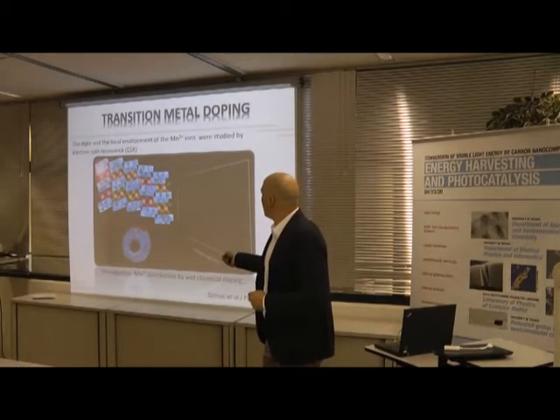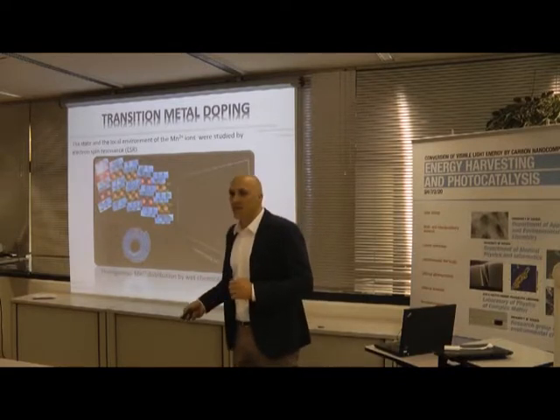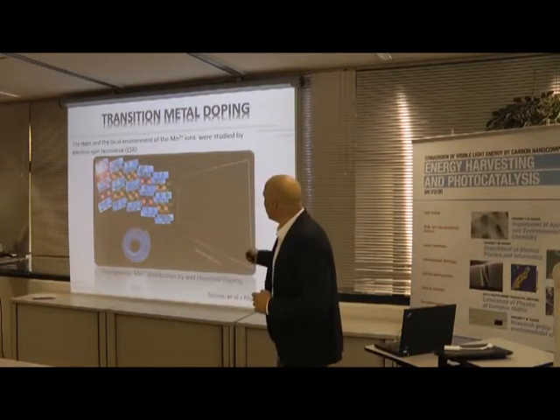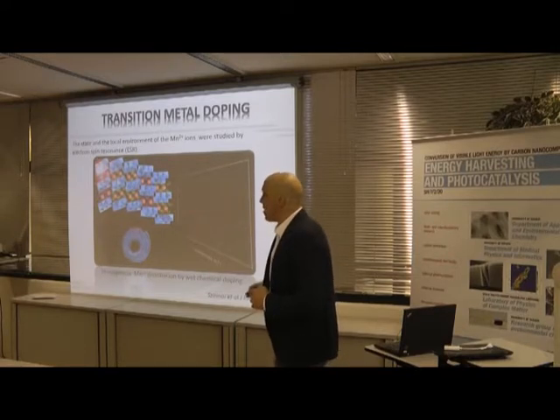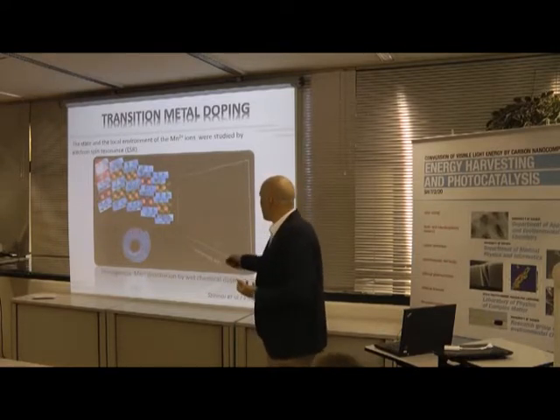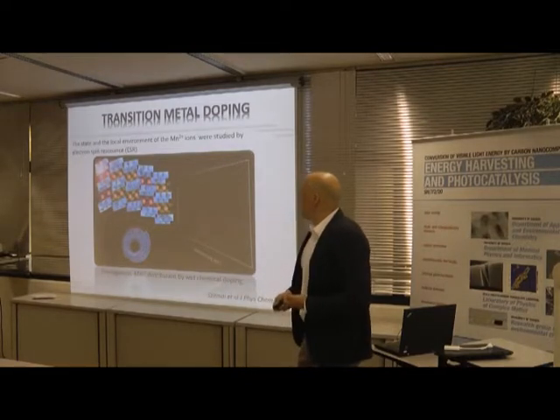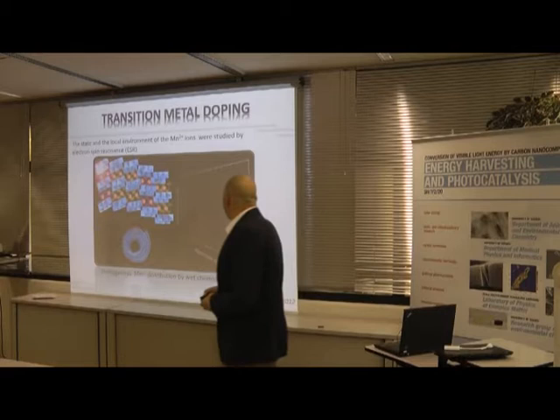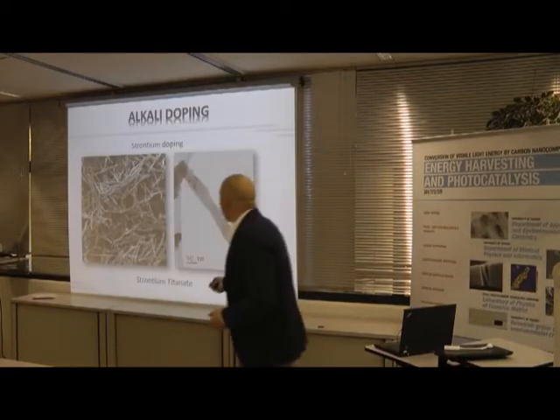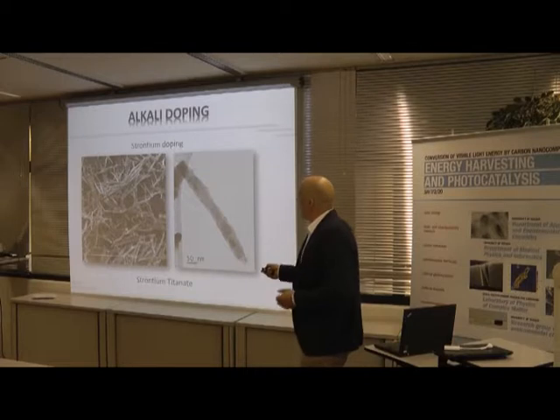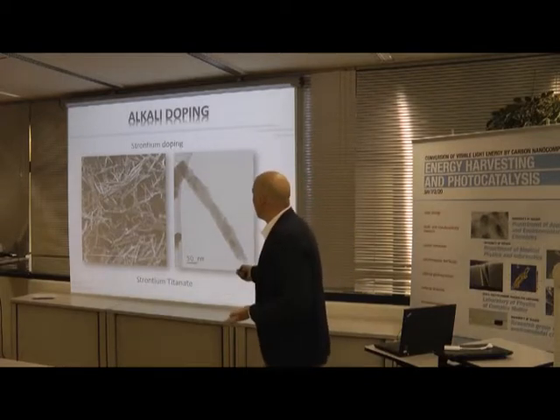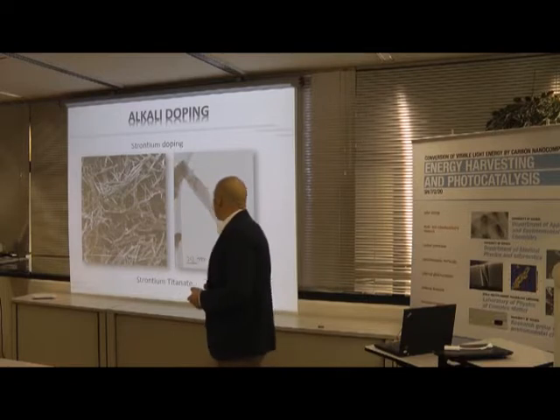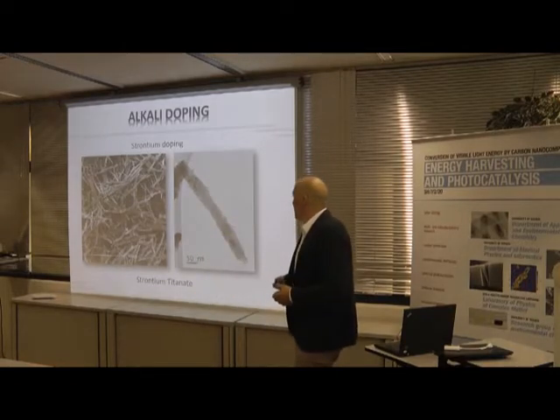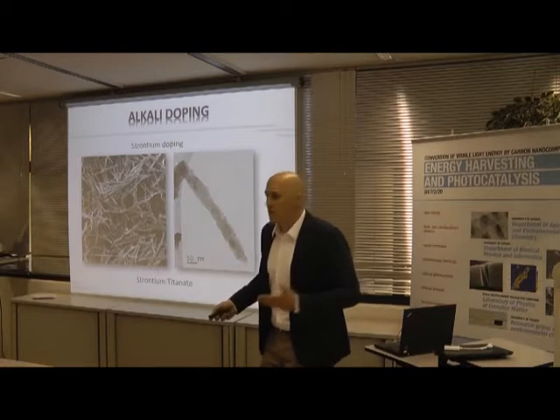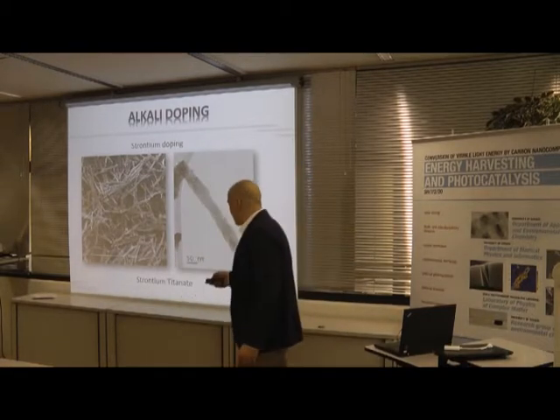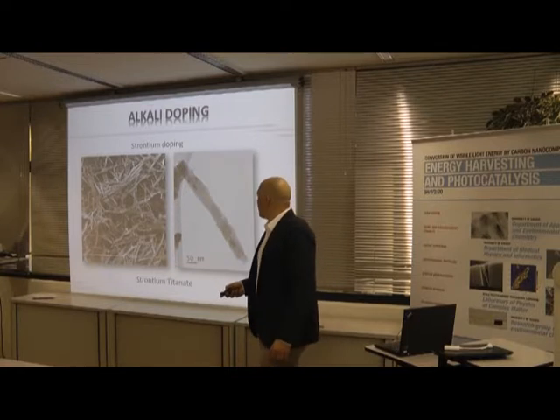Here is a case when we use the ion exchange properties of titanium nanotubes to put manganese into the structure, and that the manganese was homogeneously doped within the framework was proven by EPR, electron spin resonance, by Peter Szirmai and Bálint Nafradi. Another, we can use alkali doping. Here we increase the doping alkali ion concentration so much that we completely render the titanium oxide into strontium titanate. So this is a new type of elongated strontium titanate nanowires that we have synthesized.